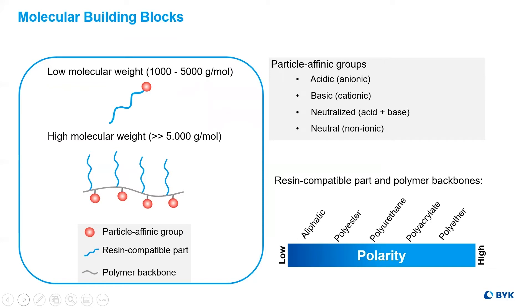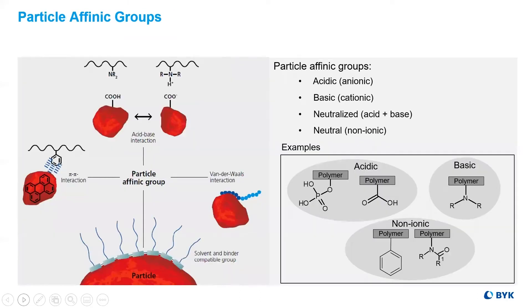Higher molecular weight polymers had more pigment affinity groups and wider ranges of compatibility. Understanding the effects of polarity became a really great indicator for additive selection. We gained a greater appreciation of the bonds of the pigment affinity groups, thereby helping formulators make better additive choices when working in either acidic, basic, or non-ionic systems. Recognizing that most systems respond best to the acid-base theory of interaction, this garners improved adsorption to the pigment surface.